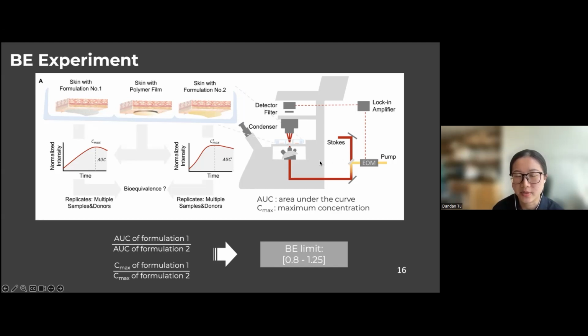This is the SRS microscope system we have in our lab. We will image those 3 samples continuously for a total of 6 hours. The measured intensity profile from the drug applied skin will be normalized to the intensity profile from the polymer film, and then we can get those normalized intensity profiles for each formulation. Using the profile, we can calculate the Cmax value and AUC value. For each formulation, we will repeat multiple skin donors, and for each skin donor, we will repeat multiple samples.